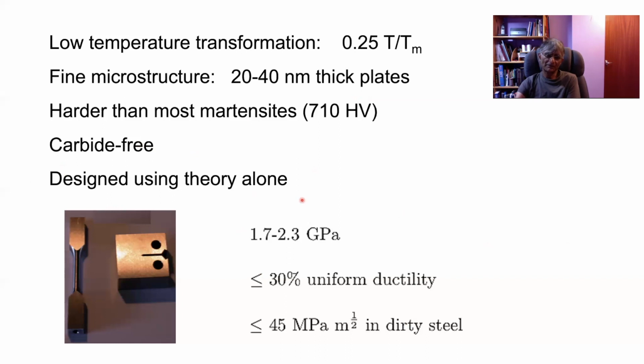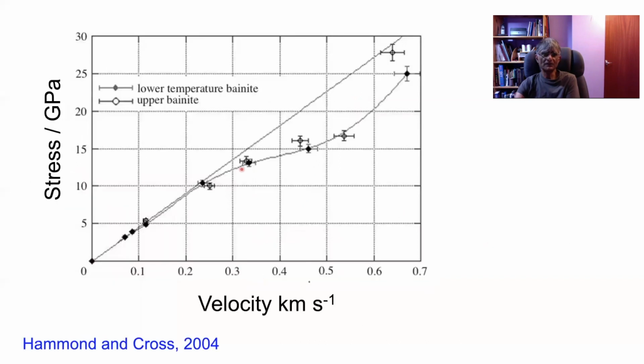And in the Cavendish laboratory, they did very high strain rate experiments. And you can see that this is a projectile being fired at the nanostructured steel we have developed. And elastic deformation ceases around here. So the material can support this high velocity impact elastically up to 10 gigapascals.